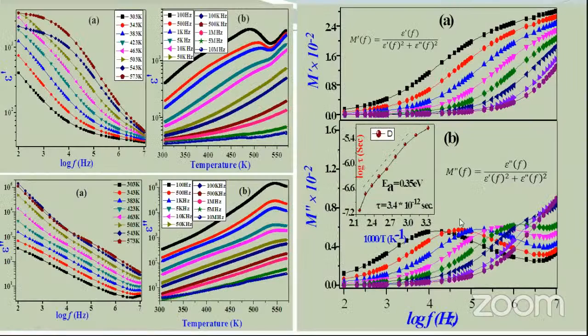And the dielectric property shows the conventional behavior, but with a high dielectric constant. And in this case, the dielectric loss is higher. This is due to conductivity relaxation. And we can see here there are some peaks. So these peaks show the relaxation process in the material. And these peaks go beyond our measured frequency range as we increase the temperature. So we have adopted the electric modulus here.